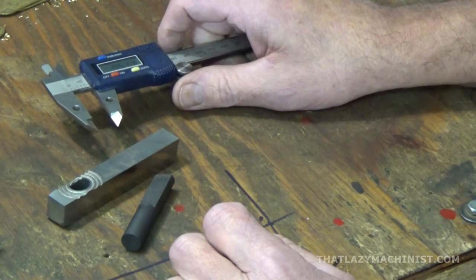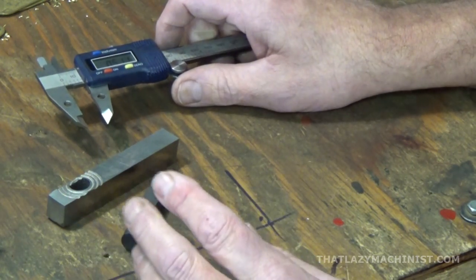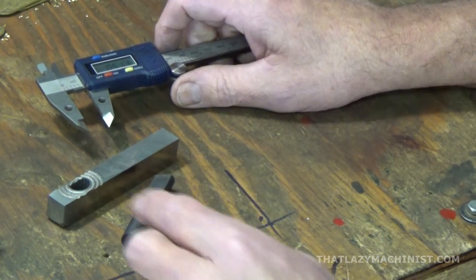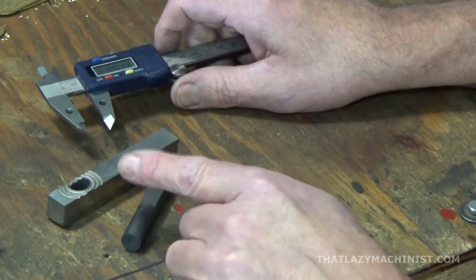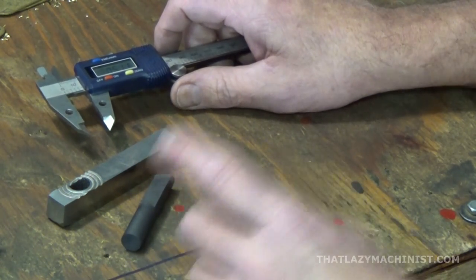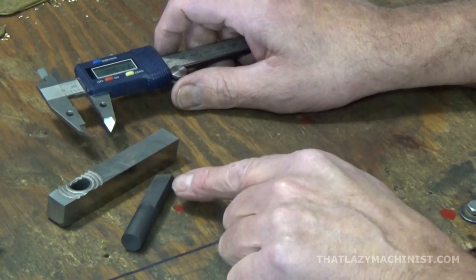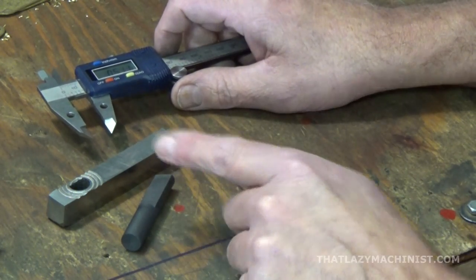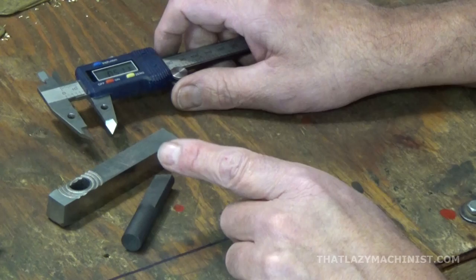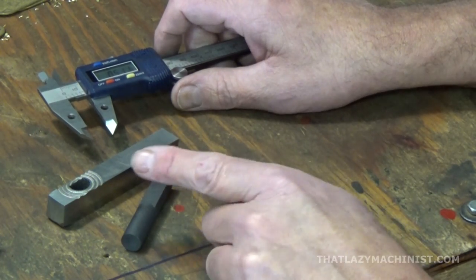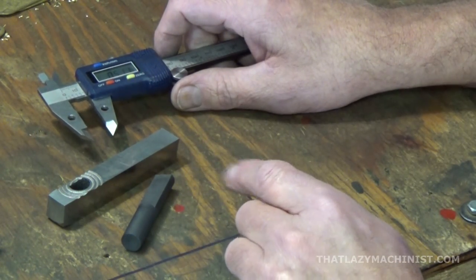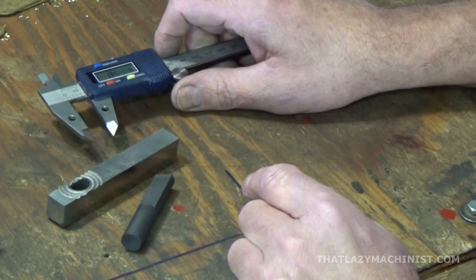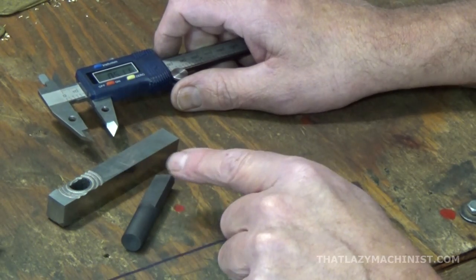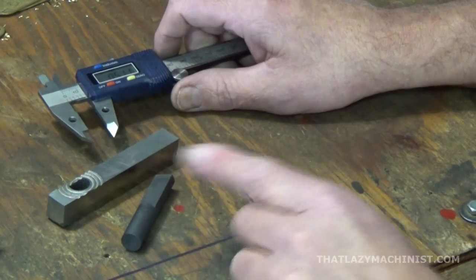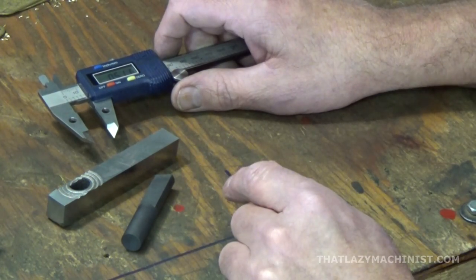Now, that's a difference of 13 thousandths of an inch, or if you prefer, 6.5 thou per side of the electrode. And that's not surprising, that's a big difference. But remember, we were doing this with a roughing cut, so there is going to be a large difference between the electrode and the part. Had I been producing a finishing cut, I could have got that distance way down, close to 1/1000th of an inch. So it really depends how hard or fast you're cutting.